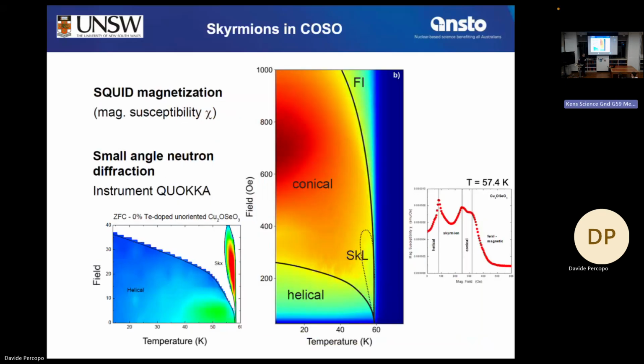So, doing that, we mapped out the phase diagram here. That's the intensity of the Bragg peaks, the helical phase, the skyrmion phase. And in addition, we did SQUID magnetization measurements. That was done here in-house, LG43 downstairs. That's a $750,000 piece of equipment, according to the company the most sensitive on this continent. So, yes. Great. And that's actually the phase diagram. It's perfectly complementary. And here the raw data from the SQUID experiment.